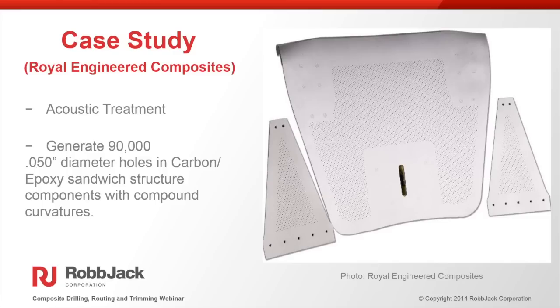And the application for that style of tool is anytime you have to do really small diameter holes, and a lot of them. A common application would be acoustical treatments for aircraft engines nacelles, blocker doors, things like that. In this application, they had to generate 90,000 holes at 50 thousandths diameter in a carbon fiber sandwich structure. And they tested about 10 to 15 different manufacturers, and each of the manufacturers may have had 1 to 5 different types of geometries that were developed to try to solve this problem.